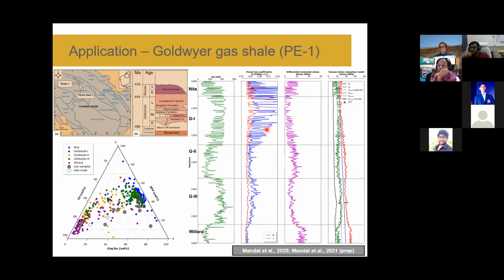So when this test runs, we measure those properties, but we also monitor any pore pressure buildup and any temperature fluctuation. That's why normally when this test is done, the whole lab is air conditioned. The air con never stops, it's running 24/7 at 22 degrees, so that the outside temperature always remains the same. Whatever inside temperature builds up, we can exactly monitor if there is any fluctuation happening or not. Okay.